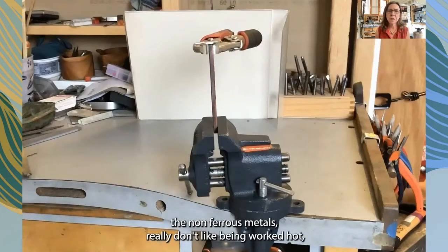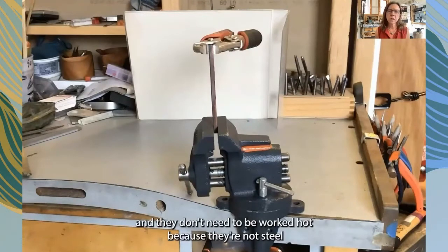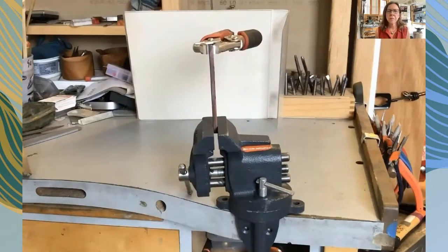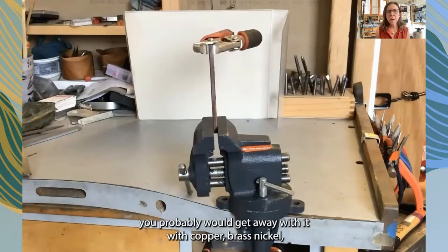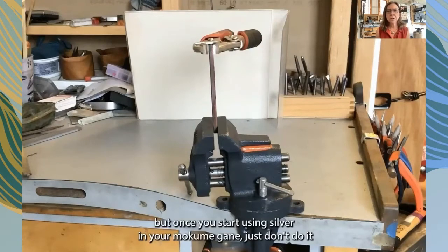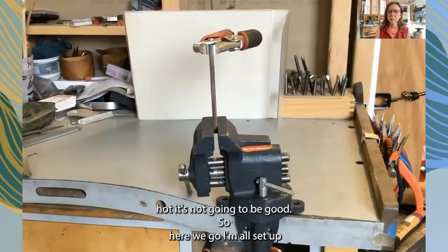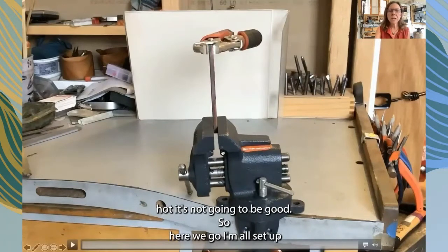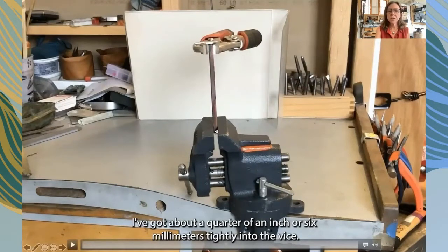The non-ferrous metals really don't like being worked hot, and they don't need to be worked hot because they're not steel. You probably would get away with it with copper, brass, nickel. But once you start using silver in your Mokume, just don't do it hot. It's not going to be good. So here we go. I'm all set up. I've got about 1/4 inch or 6 millimeters tightly into the vise.